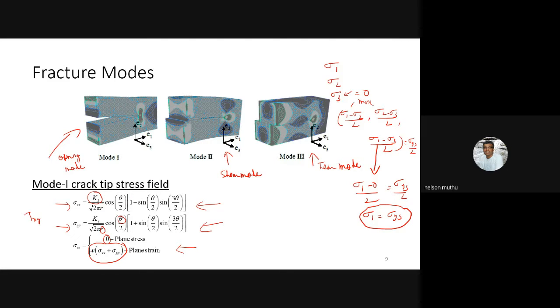So now the question is, if you take nu equal to 1 by 3, what will sigma 3 be? Sigma 3 is going to be 1 by 3 times sigma 1 plus sigma 2, right? But in this case, for mode 1, along theta equal to 0 degrees, your sigma 1 is equal to sigma 2, which we have already seen from these expressions. So it is going to be 2 alpha by 3, where sigma 1 is equal to sigma 2 is equal to alpha. Now you see here there is a non-zero stress in the third principal direction.